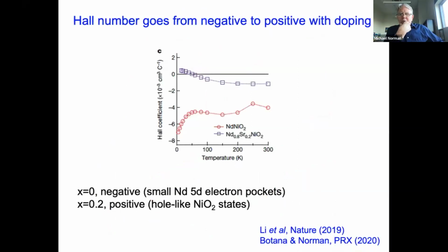The other interesting thing is, as Harold showed, as a function of doping, you have a tendency to go from a negative Hall number to a positive Hall number. And this can be understood theoretically. We treated this in our original theory paper on this in 2020. At the zero doping level, you have these 5d electron pockets from the 5d orbitals of neodymium. Those lead to a negative Hall number. And then the assumption, of course, is that the hole-doped stuff coming from the nickels is probably incoherent. But as you dope, you depopulate these 5d orbitals. The hole-like nickel oxygen states start to participate in the Fermi surface, and therefore you switch to a positive Hall coefficient.